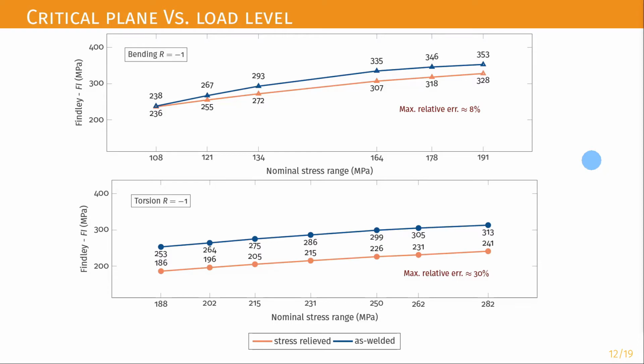Here is shown Findley's critical plane factor over the nominal stress range for pure bending and torsional loading respectively. For the sake of simplicity, the maximum relative error between stress-relieved and as-welded conditions is also shown. It is evident that under similar loading conditions, the relieving process decreases the amount of damage more for the pure torsion than for the pure bending loading.